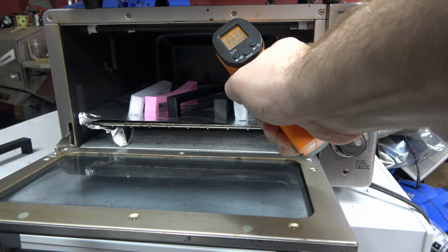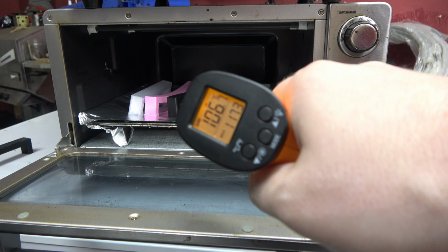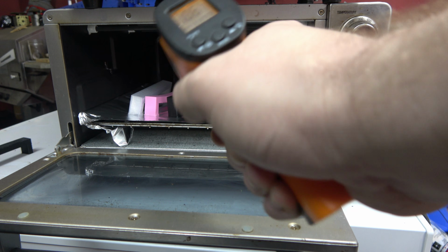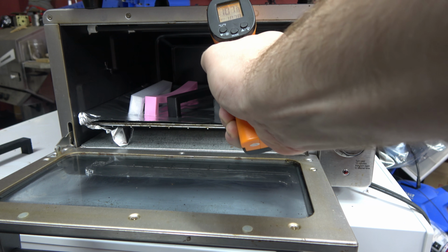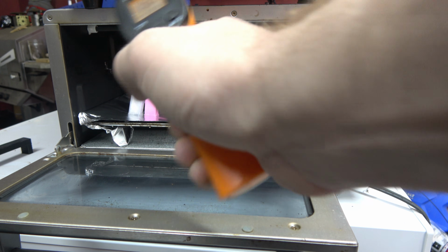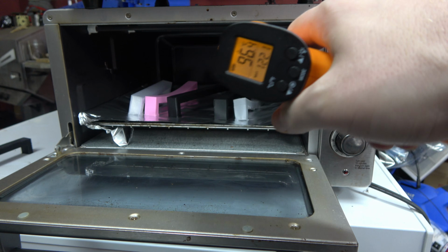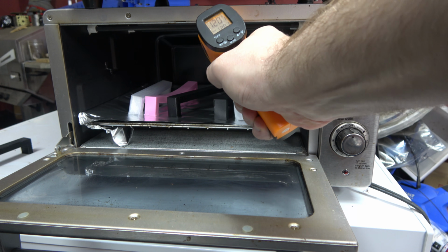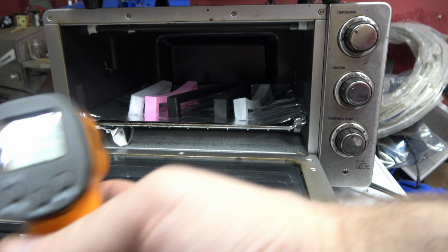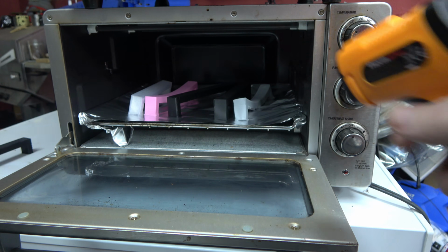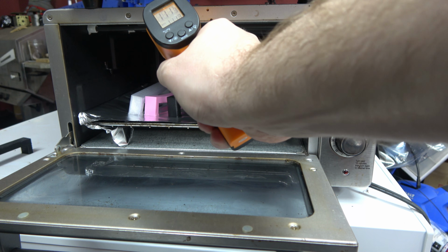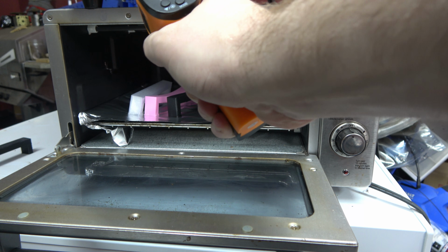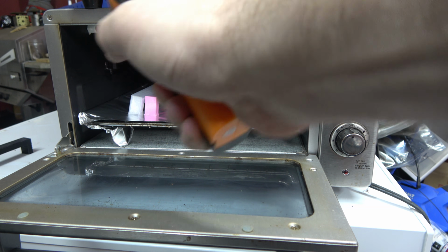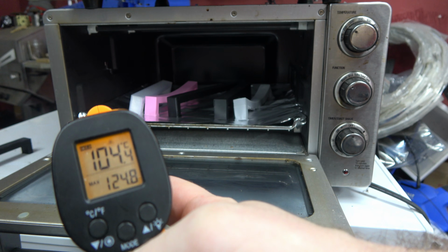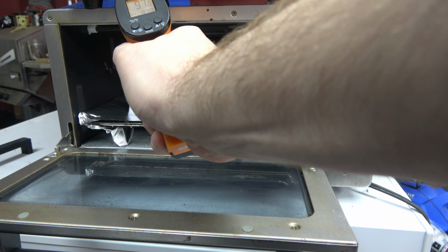Okay, so looks like the PLA made it to about 117. That piece we actually got a 122 reading on, and it did not deform. 120 degrees Celsius. That looks like the annealed one lived. The ABS got to about 124, and the polycarbonate got to about 122.